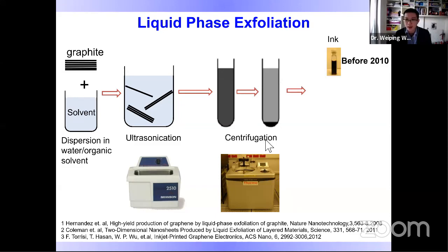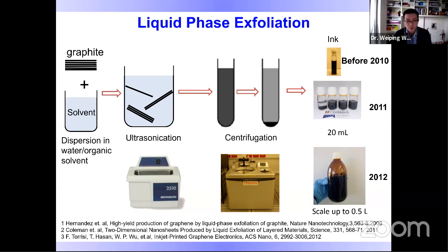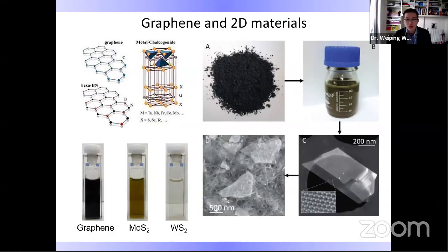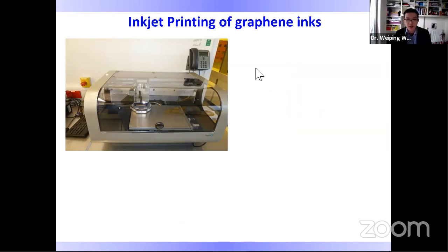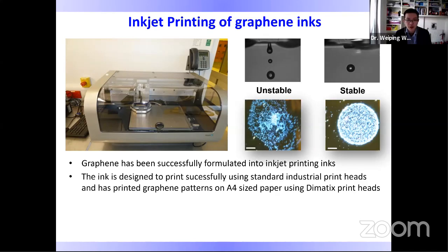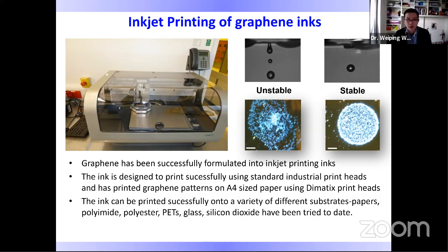Then we can get the ink at high quality from a very small amount, like 1 ml to 20 ml, then to liter scale. This ink development is very universal and powerful, and can be applied to other 2D materials like MoS2, WS2, boron nitride, and so on. Once we got the ink, we can use inkjet technology to print and pattern this graphene material onto the substrate. This helps us fabricate electronic devices on flexible substrates like paper or PET and other